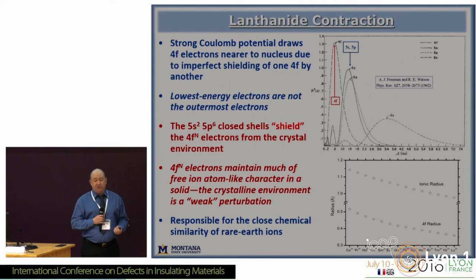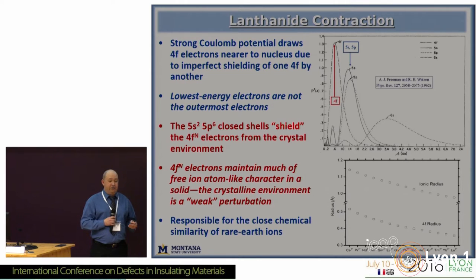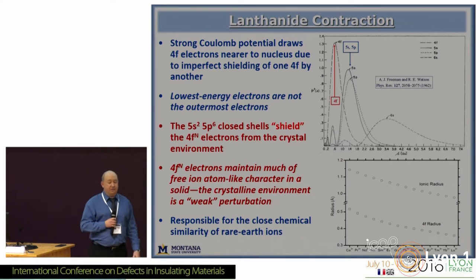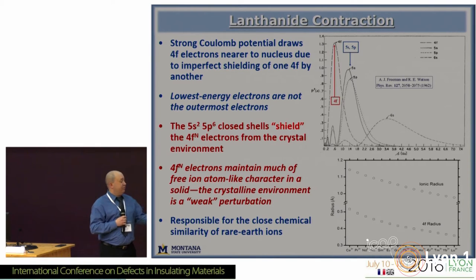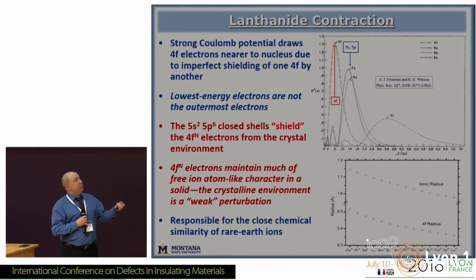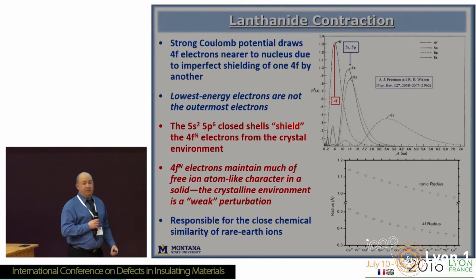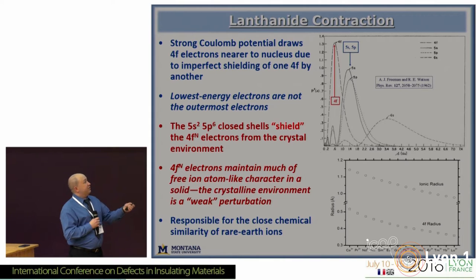Among these, the rare earth ions are very special because of the lanthanide contraction. Because of the only partial shielding of the 4F electrons from each other, they see an effectively larger central field from the nucleus, causing the 4F electrons to be pulled in towards the nucleus. Even though they are the lowest energy unfilled shell, they're actually within the orbital radius of the filled 5S and 5P shells. This means the 4F shell has very little extension beyond the outer radius of the ion, so the outer electrons provide a buffer between the ligands and the 4F shell, giving them very weak interaction with the environment. Here we can see the average 4F radius is less than half of the traditional ionic radius.